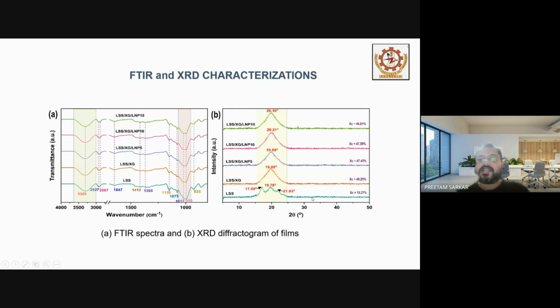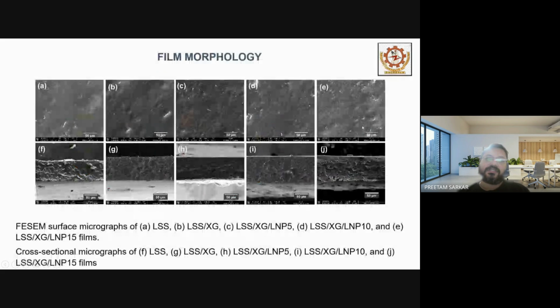As we increase the LNP percentages, the XC, the percent crystallinity, was also calculated. It increased from 15 to 48%, and then to 47 and 44.8%. Then these are the field emission scanning electron microscopy, FESEM, images of the profiles of the films, both the surface and the cross sections of these bio-nanocomposites.